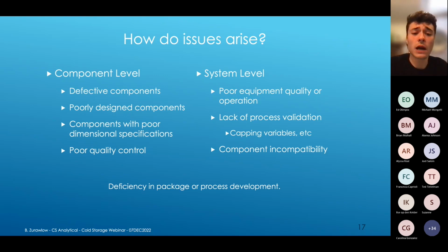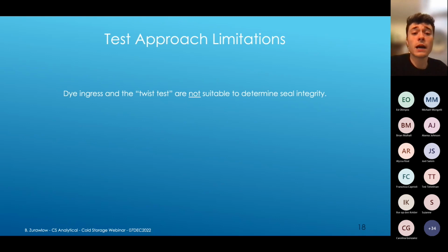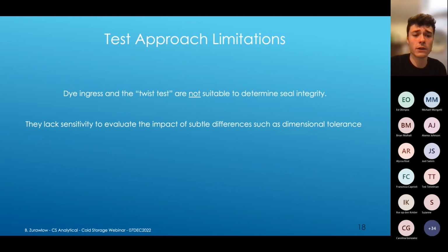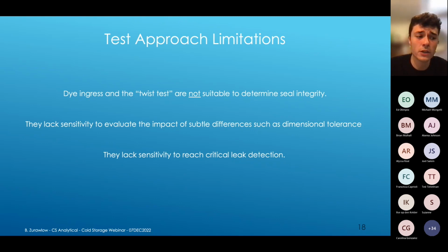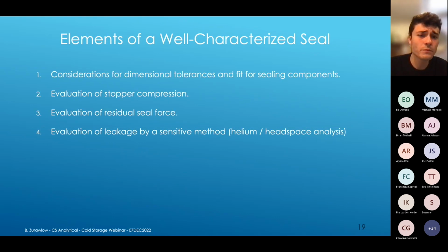So ultimately, issues arise from some deficiency in the package or process development phase in most cases. We should note that dye ingress and the twist test, the simple act of taking a crimped vial and twisting that crimp seal to see if it's tight, are not suitable to determine seal integrity. These tests are not sensitive. In most cases, they're not even applied as leak tests, and are really unable to differentiate between very subtle differences like dimensional variation of components. And so realistically, these things individually, as we go through the life cycle of this package system, are not sufficient to really demonstrate the integrity throughout the life cycle.